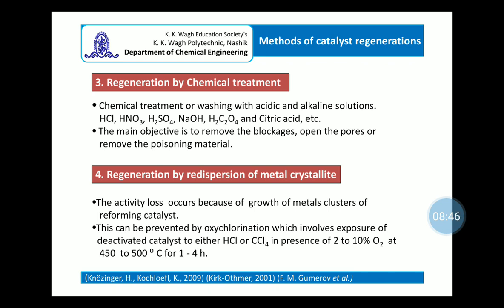One of the treatments suggested is oxychlorination. It involves the exposure of the deactivated catalyst to chlorine compounds like hydrochloric acid or carbon tetrachloride in the presence of 2 to 10% oxygen at 450 to 500 degrees Celsius for a period of 1 to 4 hours. This results in a redispersion of the metals, which are in the form of metal clusters.